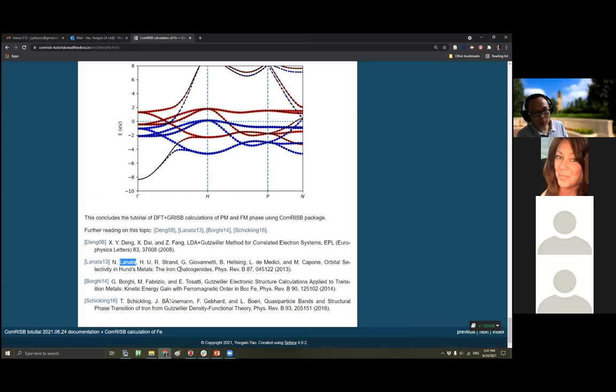And from that, up to realistic materials, these iron pnictide systems, you can see this orbital differentiation, and there are some particular orbitals, the dxy orbital, right? It is particularly sensitive to the Coulomb repulsion, and has a smaller renormalization factor, or effectively a larger mass. And I think on the first day, Gabe also presented it, on the series of iron pnictides, how the effective mass of the orbitals varies across different systems. And here we can give similar information.